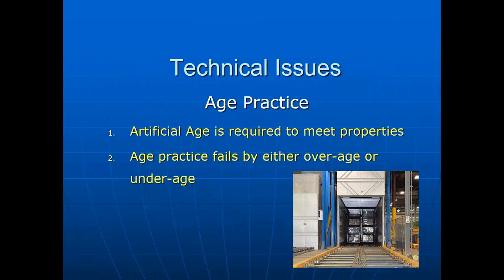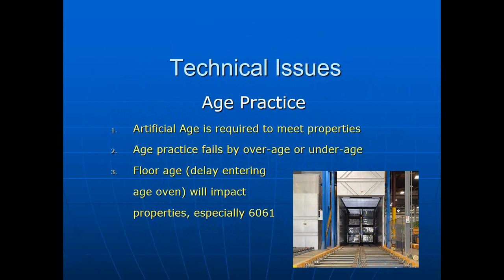Then, once the lineals are extruded and cut into mill lengths, they're run through an artificial age practice. Artificial age is required to meet T5 or T6 properties. Age practice fails by either overaging or by underaging. So there's a specified window that has to be met. And finally, floor age or delay between the time a lineal is extruded and when it goes into the age oven will impact properties. And this is especially true of the alloys with excess magnesium like 6061 and 6351.